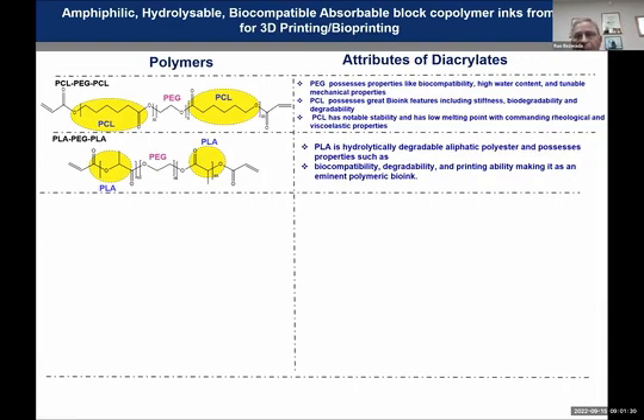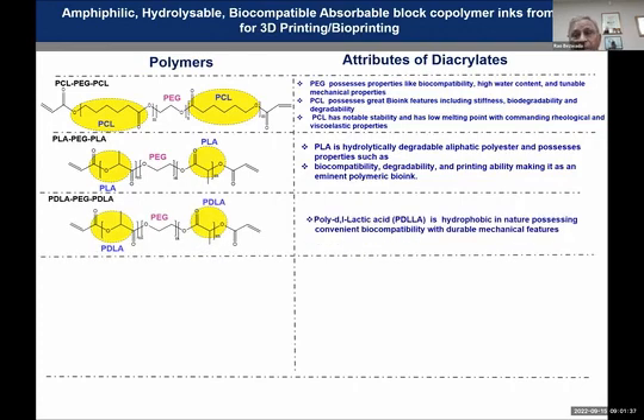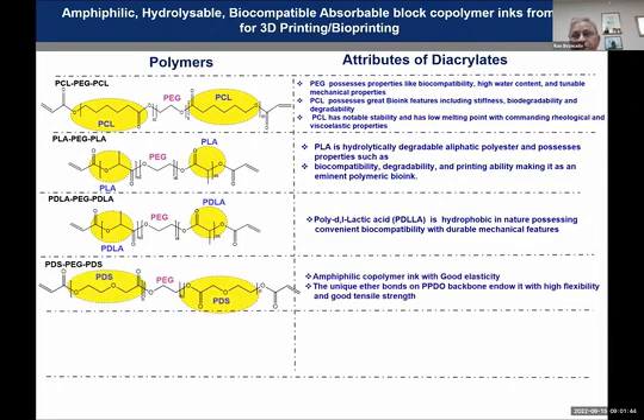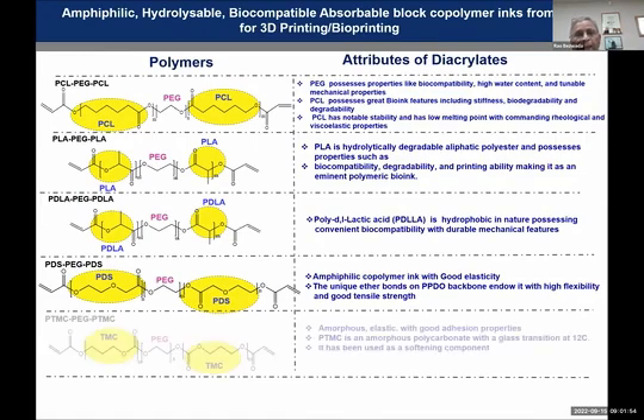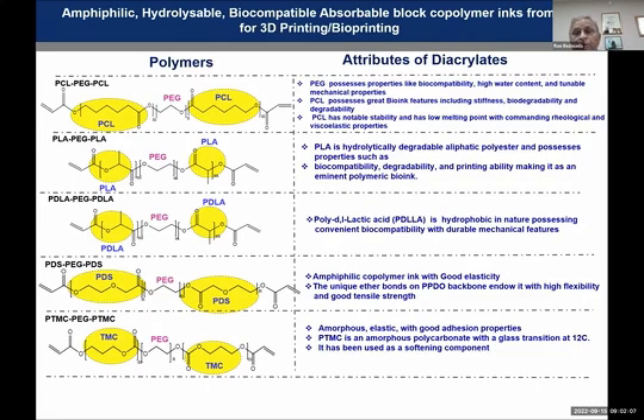So we make PLA, which is going to be a stiffer molecule, but with slower absorption. DL-lactide is stiffer, amorphous, but with faster absorption. PDS polymer is a monofilament elastic polymer, which gives strength and elasticity to the bioink. And we also introduced TMC. TMC is a very elastomeric, rubbery polymer, and it has very good adhesive properties. So for cell adhesion, it could be very useful.